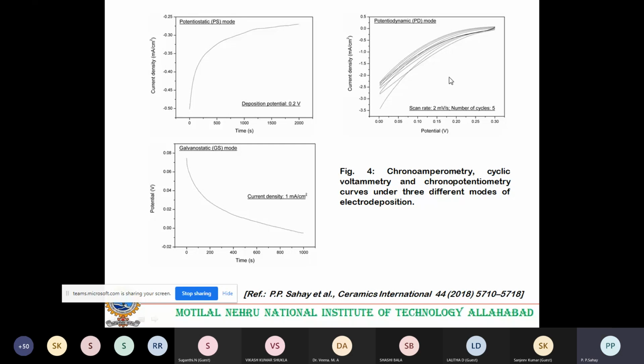So why do these changes occur? This is attributed to the deposition of MnO2 film on the working electrode during the preceding cycle. Because if one cycle is complete, some amount of MnO2 will deposit. When the second cycle repeats, it will be influenced by the previous deposition of the MnO2.